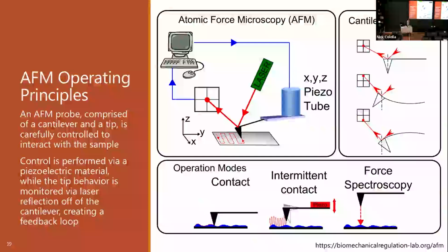So the AFM is a more complex instrument. We're going to have a cantilever that's going to indent on your sample. We're going to align the laser so it bounces off the back of the cantilever and then hits a detector so we can see exactly where the cantilever is. As the cantilever moves up and down, as it pushes into the sample, the laser spot on the detector is going to move. And for us, we're going to be doing force spectroscopy, where we push into the sample at many points.